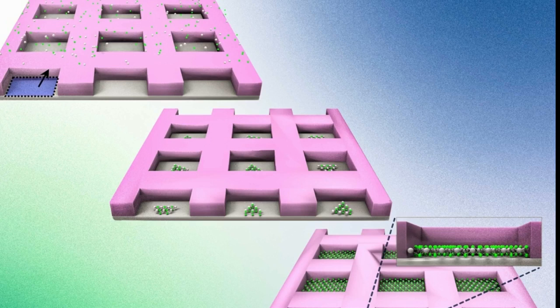To do so, they first covered a silicon wafer in a mask — a coating of silicon dioxide that they patterned into tiny pockets, each designed to trap a crystal seed. Across the masked wafer, they then flowed a gas of atoms that settle into each pocket to form a 2D material — in this case, a TMD. The mask's pockets corralled the atoms and encouraged them to assemble on the silicon wafer in the same single crystalline orientation.